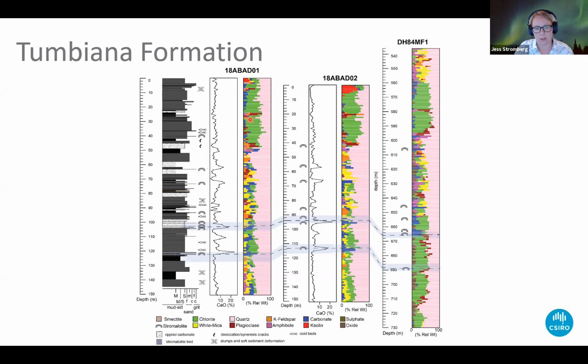And especially in these two holes where you got that kind of plagioclase little bit here. But what's really interesting, I think, is that if you throw the chemistry in this bottom of the hole where it's maybe a bit more difficult to correlate, you can look at these carbonate-rich units, which are also calcium-rich, and they're stromatolitic units. So they're actually logged as stromatolite. So if you combine the geological logging, the geochemistry, and the hyperspectral mineralogy, you get a really clear correlative unit